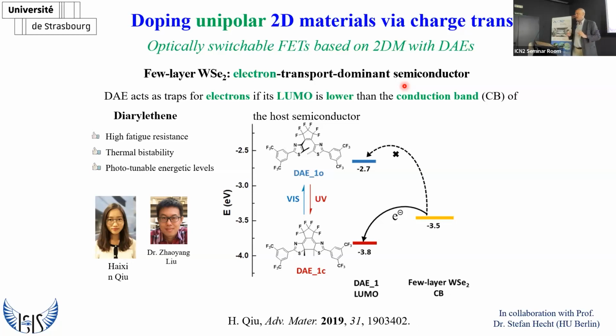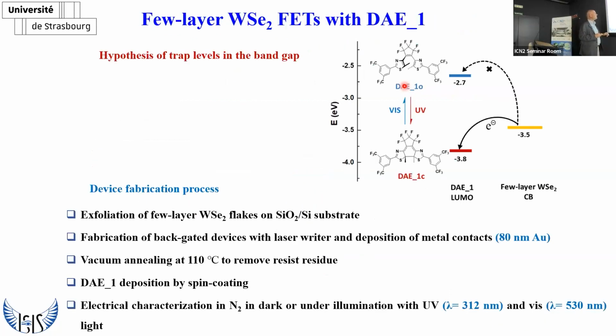What does it mean if you have a state of the dopant that is inside the band gap of the semiconductor? It means that this molecule, our dopant, will behave as a trap for the charges of the semiconductor. Whereas if the molecule has a level that falls out of the band gap, the interaction is purely electrostatic. So essentially we can dope and undope our material by changing the state of the diarylethene.